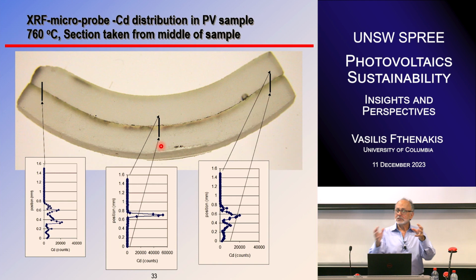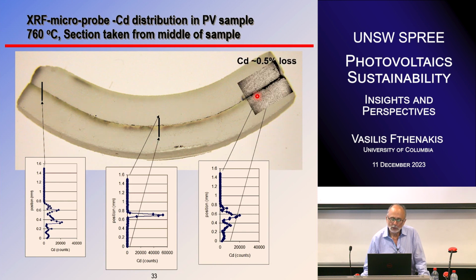What is emitted, we measure from the ICP analysis of the acidic liquid in the scrubber. But it's obvious that the losses happen before the two glasses fuse together. You can see an opening here. The black is the decomposition products of EVA that burns at those temperatures. And you have some vapor pressure of cadmium at 760, not high, but a few torr there. So some cadmium has been a vapor and went out with the byproducts of the combustion.